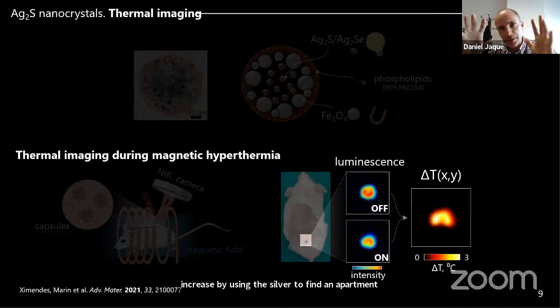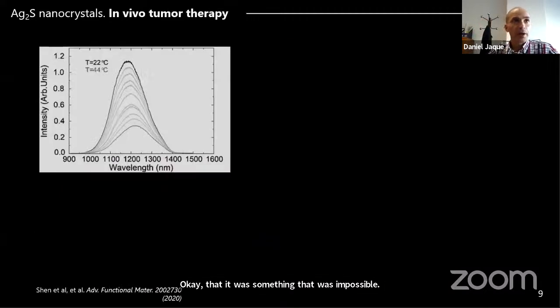And this is the thermal image of this subcutaneous injection. And we can see that the temperature increase induced by the magnetic field is as low as 3 Celsius, but we are able to measure it. So the magnetic field is making the magnetic nanoparticles heat, and we are registering the induced temperature increase by using the silver sulfide nanoparticles. And this is done without touching the animal, just using light. One important thing is that these results make it possible to monitor in real time the temperature during magnetic hyperthermia treatments. That was impossible without this technology.